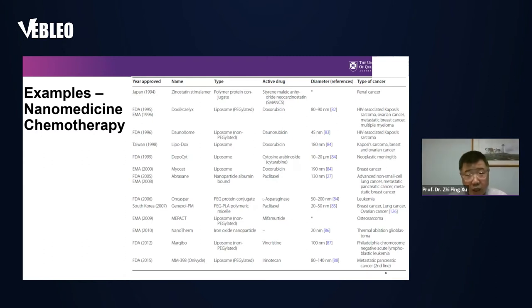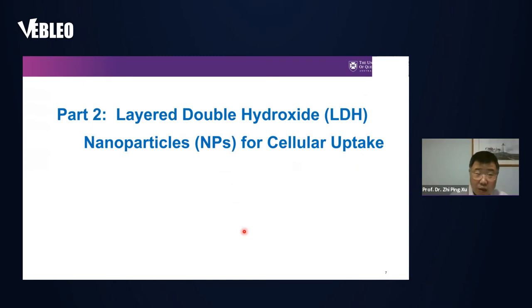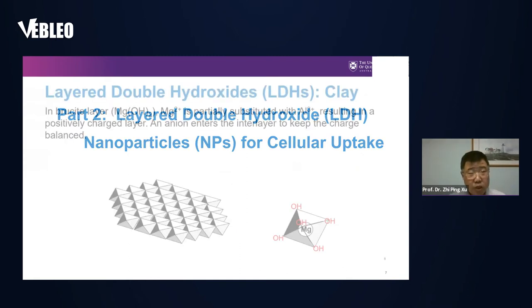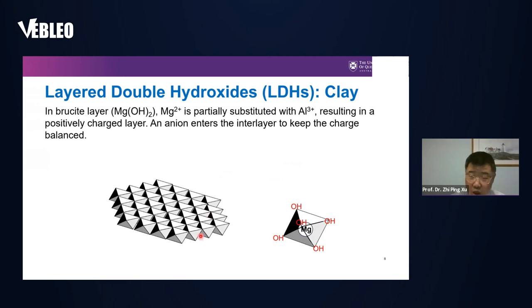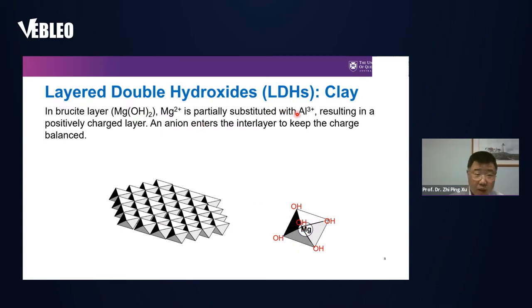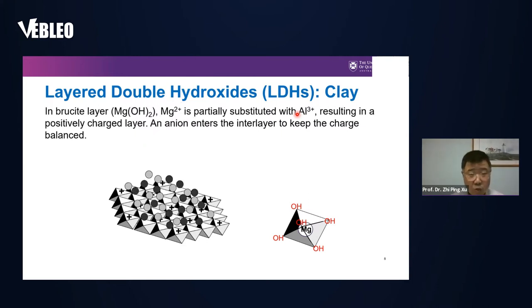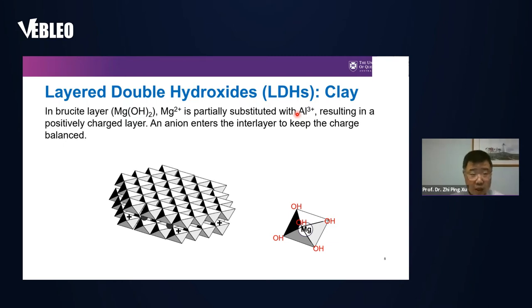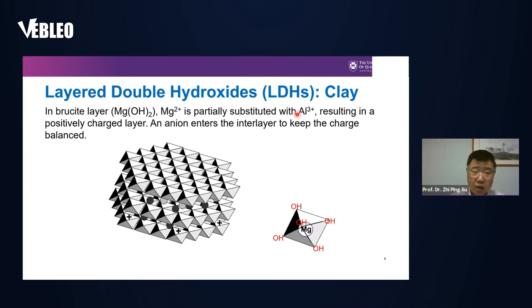LDH nanoparticles are a specific clay material very similar to brucite in structure — brucite is magnesium hydroxide. In each octahedral unit, there is one magnesium surrounded by six OH groups. When they share edges and form two-dimensional sheets, the structure is charge-neutral. If magnesium is replaced by aluminum, the octahedral becomes positively charged, absorbing anions and water molecules to form a sandwich-like structure, and multiple layers together form three-dimensional nanocrystals.